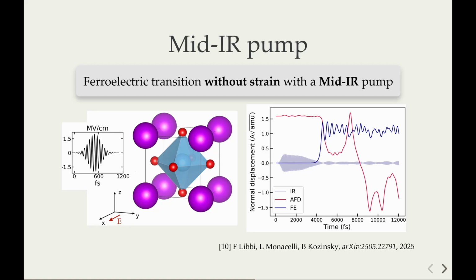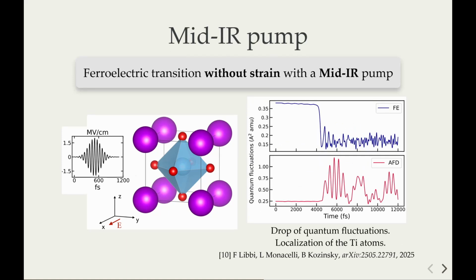You see that after 4 picoseconds, it spontaneously goes into a ferroelectric state and remains there for a long time. At the same time, if you look at the quantum fluctuation of the titanium atoms, especially in that direction, we observe a drop exactly at that time scale - this is the antiferroelectric mode, and it instead goes up in fluctuation.